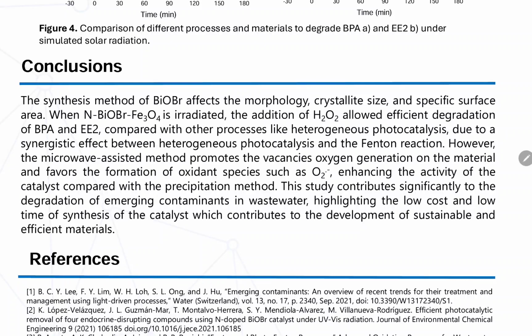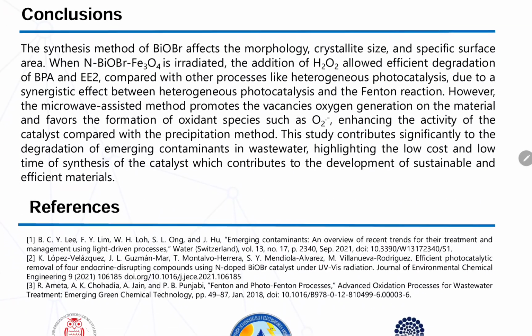However, the microwave synthesis method promotes oxygen vacancy generation on the material and favors the formation of oxygen species such as superoxide radical, enhancing the activity of the catalyst compared with the coprecipitation method. This study contributes significantly to the degradation of emerging contaminants in wastewater, highlighting the low cost and low time of synthesis of the catalyst, which contributes to the development of sustainable and efficient materials.